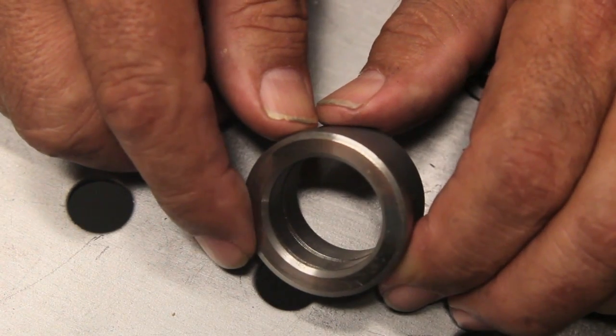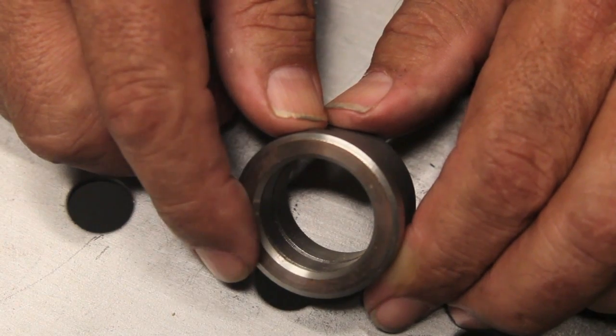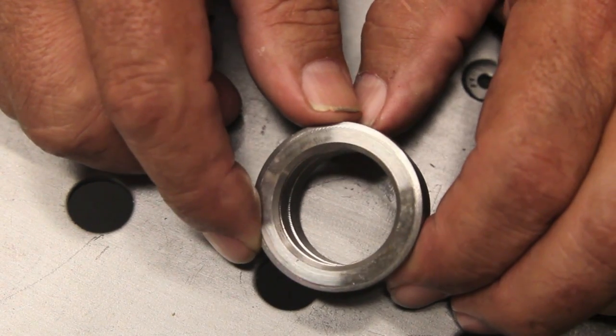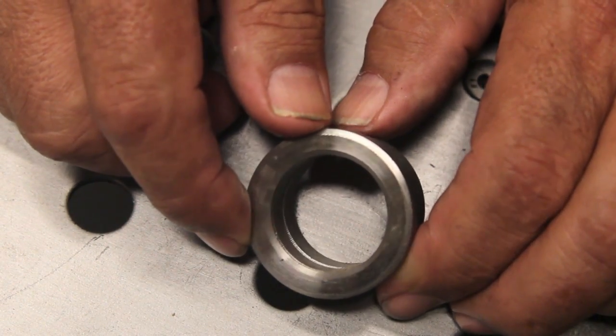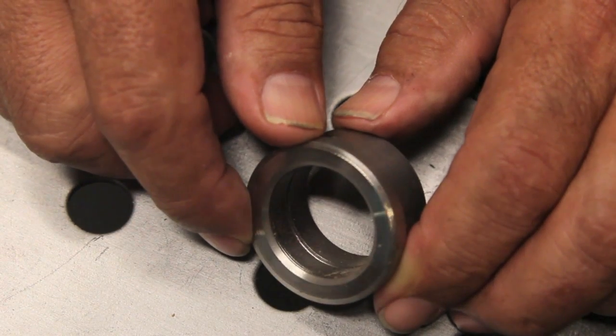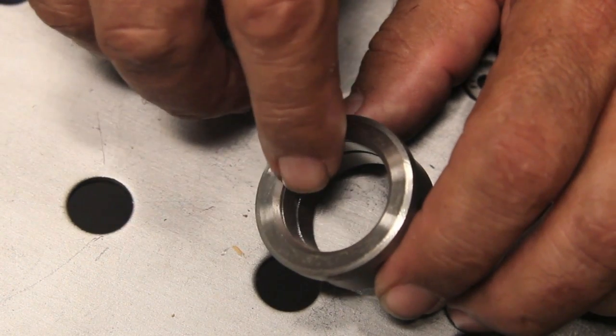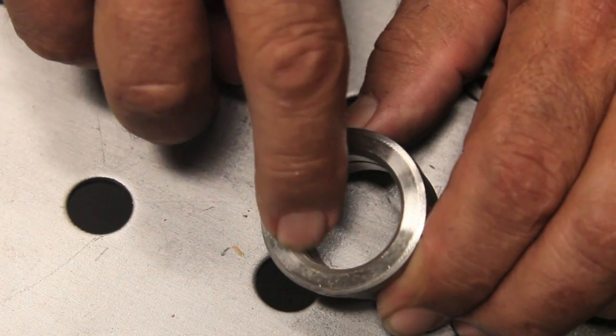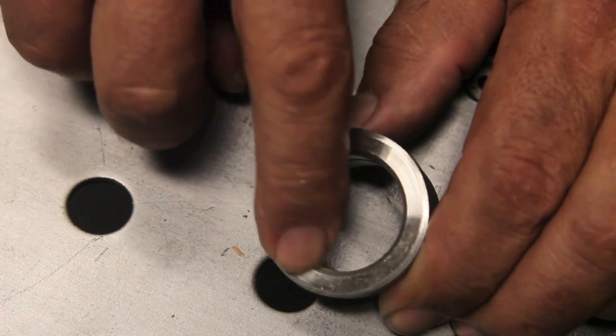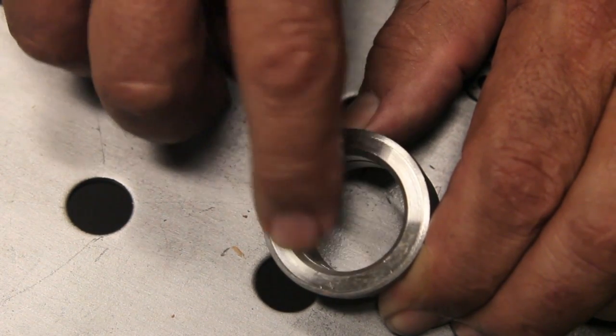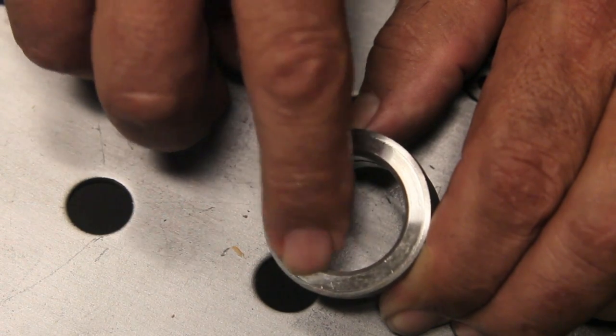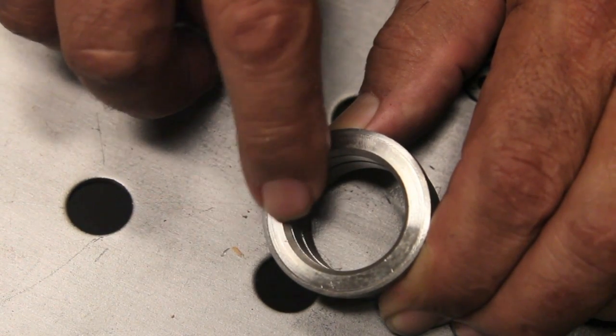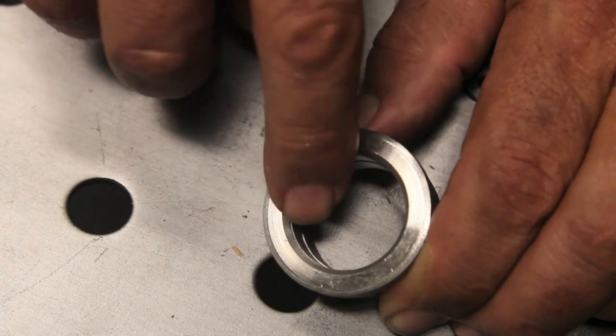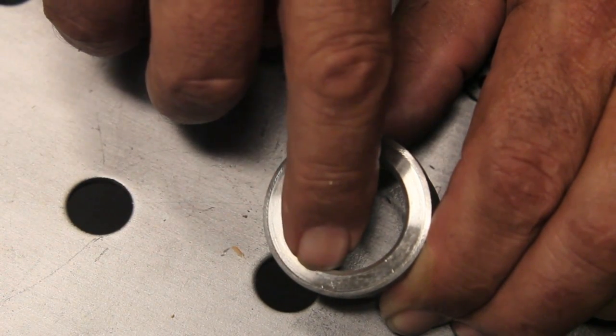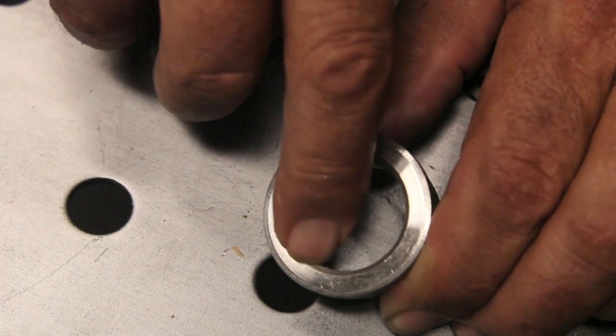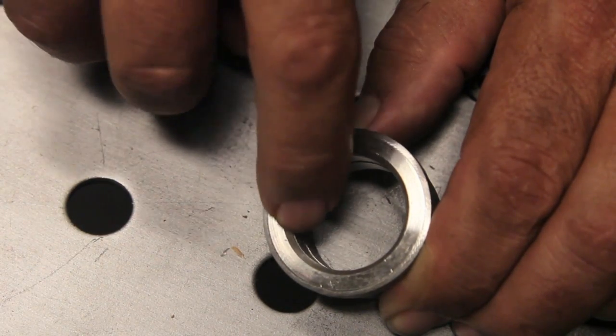You would think that high speed pulsing that fast would be like no pulse at all. It's not like no pulse at all. It has an effect. It's not like night and day. It just has an effect. And so for build up like this, this would be also very similar to tool and die repair, where something is worn and you are building it back. A lot of times with a hardenable rod, and it will be machined back off and reheat treated. You can precisely place a bead using pulse better than you can without pulse. That's been my experience.